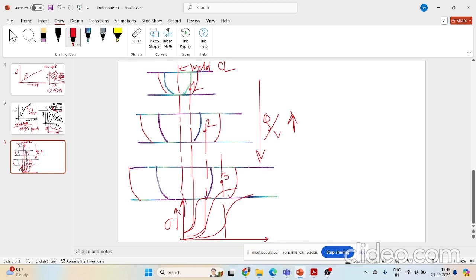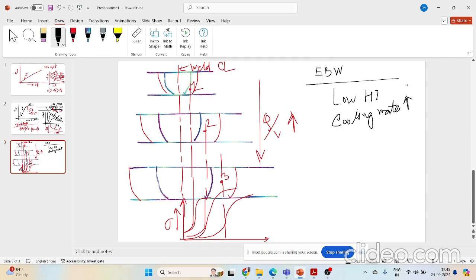Now, can you tell me, in electron beam welding, will you see more recrystallization or less recrystallization? What happens in electron beam welding? In electron beam welding, it offers low heat input, right? You will have low heat input and the cooling rate is higher. The cooling rate is very high in electron beam welding. So very little recrystallization is observed in the heat affected zone of your work hardened material.